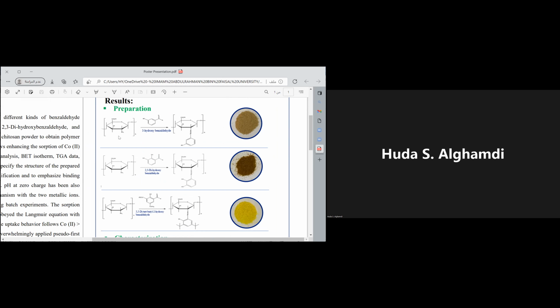What we did here is this is Chitosan, and this is the first monomer we added to the matrix of Chitosan. So we achieved the Schiff base compound polymer, and this gives me a more stable and more robust polymer. Okay, so the first polymer we added 3-hydroxybenzaldehyde, and the second one we added 2,3-dihydroxybenzaldehyde, which has two hydroxyl groups. So these will contribute to catch the metal ions perfectly. And actually, this polymer achieved a good result.